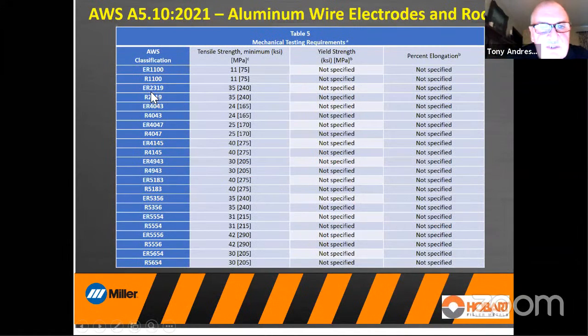And what you'll see here, just for your interest, we have 4043 coming in at 24 KSI. This is the minimum guaranteed strength. It's not the typical, it's a little bit below the typical. But the interesting thing here is we see 4943, which is the new 4000 series, and it comes in at 30 KSI. So 24 to 30, substantially higher. And again, this is not the typical, as it is the minimum. The typical would be slightly higher. So all these figures here have been around for a long, long time, except the 4943, which we just got together by testing.